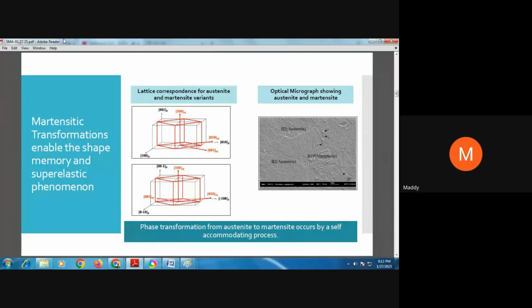Without going into detail on twinning, if you look at the two crystal structure schematics here, these are called the variants for martensite. The black outline is your cubic austenitic unit cell, and the red one is the martensite unit cell after the phase transformation is completed. For the sake of simplicity, what you see here is a cube to an orthorhombic crystal structure. But in reality, there is also a distortion involved, which makes the orthorhombic transition to a monoclinic structure. So in the austenitic phase, you have a cubic structure, and in the martensitic, the low temperature phase, you have what's called a monoclinic structure.